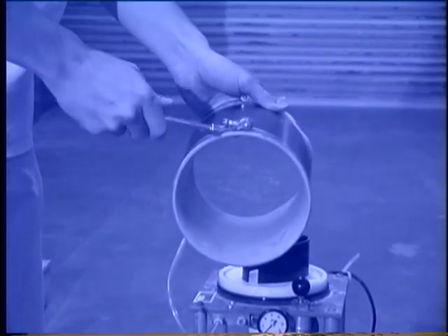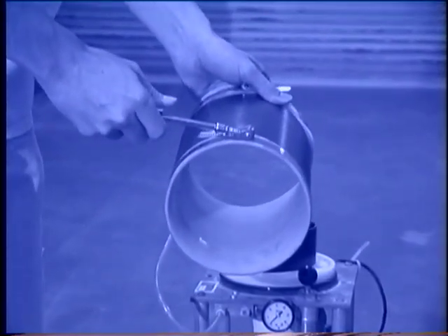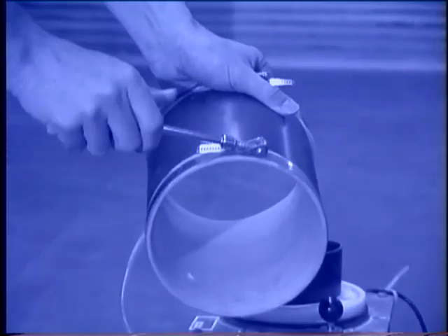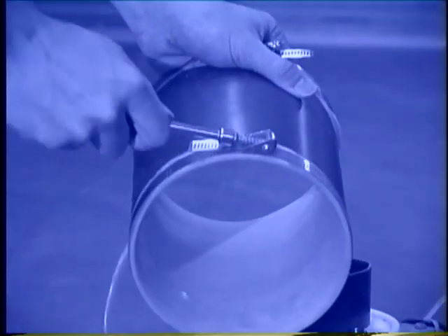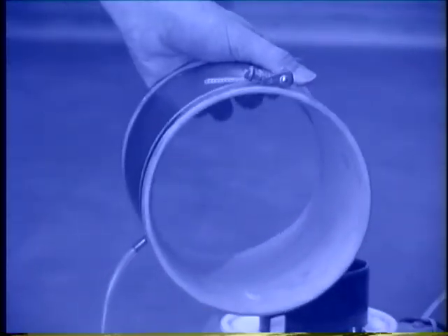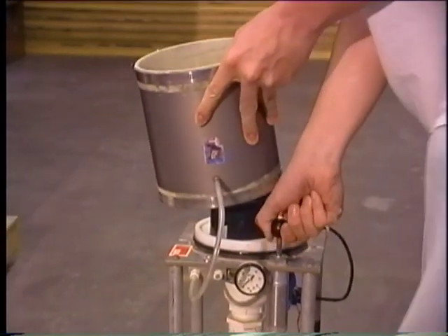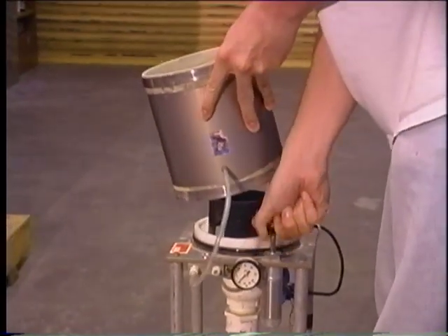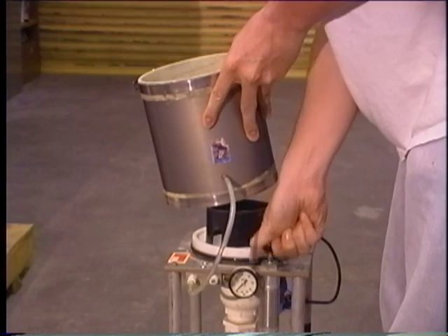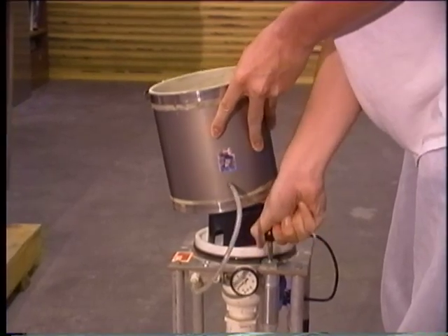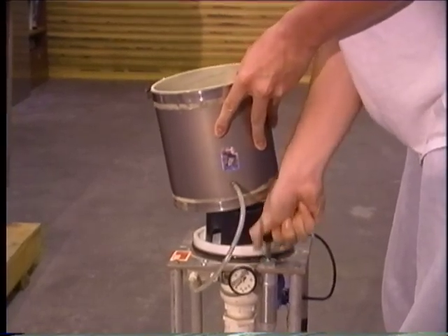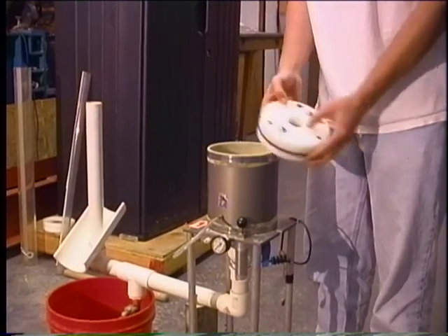Place a flexible membrane around the inside of the sample chamber. Make sure that the clamps are secured tightly around the membrane. Connect the pressure line to the vacuum nozzle. Remove the air from between the membrane and the wall of the test chamber by pumping the vacuum. This allows the chamber to fit around a 6-inch test specimen without tearing the membrane.